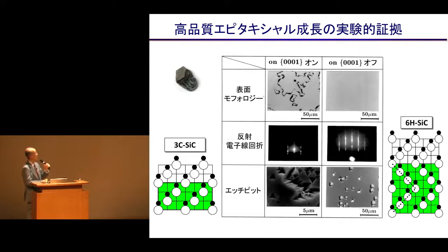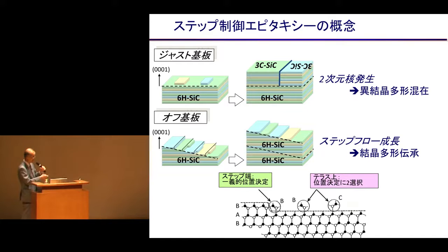And so we always find this mosaic pattern on the surface. In this industrial material, the white is silicon and the black is carbon. There is a repetition forming a zigzag pattern, and it goes back every 6 times. Compared to that, in the case of silicon or gallium arsenide, there's only a single direction. If we put it on the off substrate and on the substrate and did a comparison, just observing the surface, we can see that the stacking sequence is repeated on the off substrate, but for the on substrate side, there will be symmetry created.